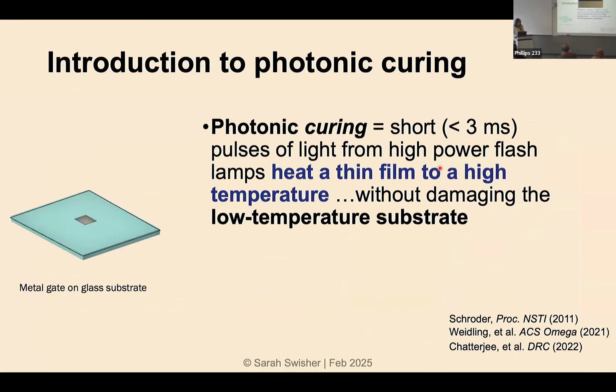So what I'm showing here is a glass substrate. And on that glass substrate, we have a small metal gate area. Okay, so this would be, for example, the bottom gate for an IGZO TFT. Photonic curing uses pulses of light from a flash lamp. So imagine the flash from a camera. That's actually how they started. They're short. They're not laser short, or pulse laser short. They're less than a few milliseconds. And you can heat the top of the thin film without damaging the low temperature substrate. And we do that by very carefully choosing our materials so that the heat stays at the top.